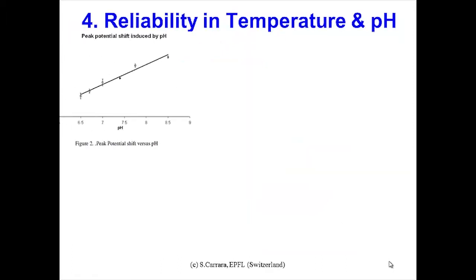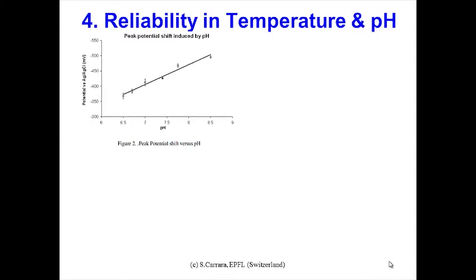What about temperature and pH? I promised you to show that if we want to target, for example, the position of the Faradaic peak in our cyclic voltammograms, unfortunately, if we vary the pH, this peak shifts in potential. And if you pay attention to the scale here, we move, roughly speaking, from minus 370 up to 470, no, more than 500 millivolts. So it's a huge variation of the potential. And if you recall the example of the cytochrome 2C9, the variation in distinguishing diclofenac and tolbutamide, for example, was 20-30 millivolts. So it's so important to take the pH into account.